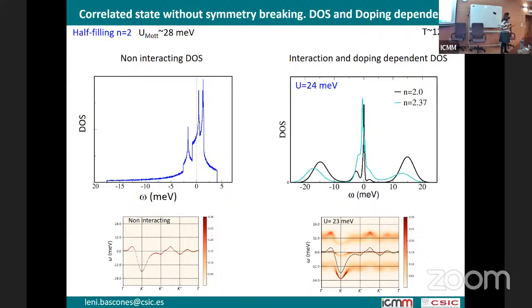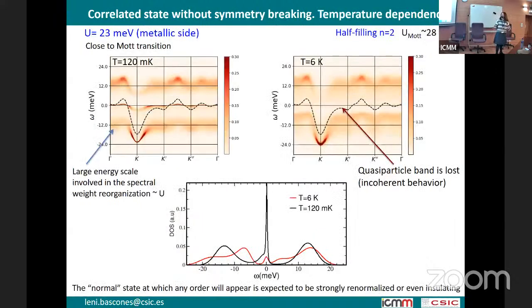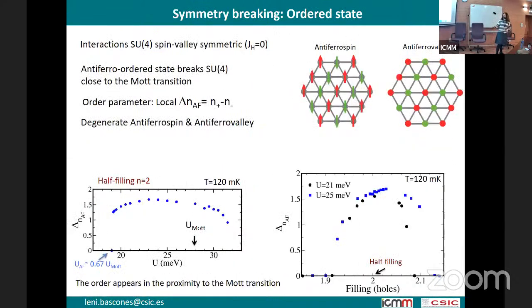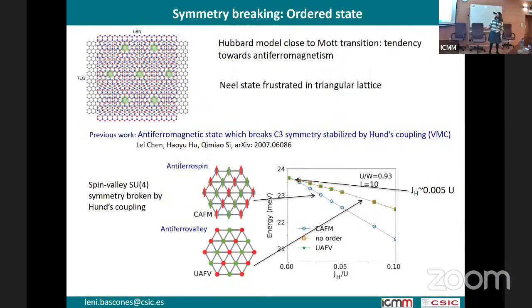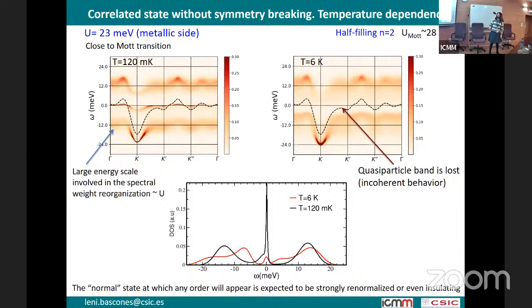Now, the ordered phase that we observe is associated to the local physics. We only observe this ordered state when we are very close to Mott. This physics is a kind of exchange, superexchange physics, so the ordering is more coming from these local electrons which are associated to the Hubbard bands. So we observe the ordering both in the metallic state close to Mott, when we have this strong coherence peak, and in the insulating state, where we don't have it.